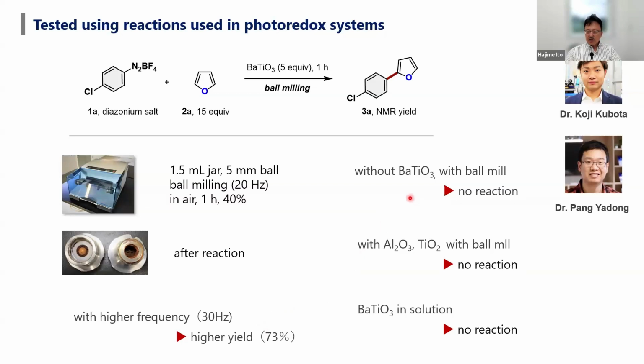Without barium titanate, only ball milling cannot show any good reactivity. Aluminum oxide and titanium oxide, which have no piezoelectricity, show no reaction. Barium titanate in solution, gently agitated, also shows no reaction.